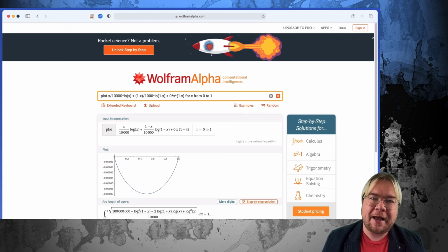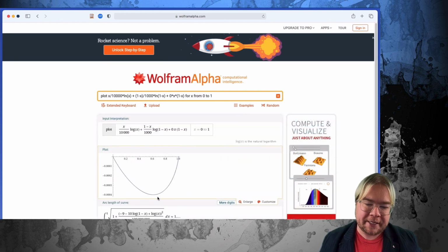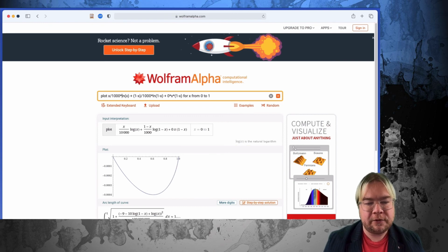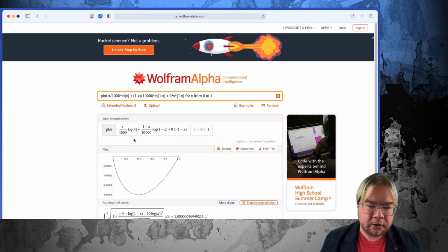Actually, very quickly, let's see what happens if we have an asymmetric blend. So you see that the degree of polymerization of B is 1,000. The degree of polymerization of A is 10,000. And still the chi parameter is equal to 0. And so we can see what this looks like. It'll be skewed. So when your molecular weights are different, it'll skew the graph. And you see, once again, it's skewed to higher volume fractions. And if you were to set this equal to 1,000 and instead have a larger molecular weight for B, then it'll skew it the other way. So you can see now it's been skewed to lower volume fractions, and the value is still what it is.